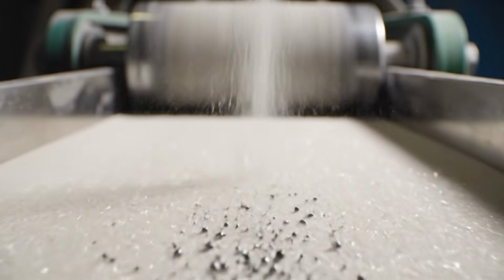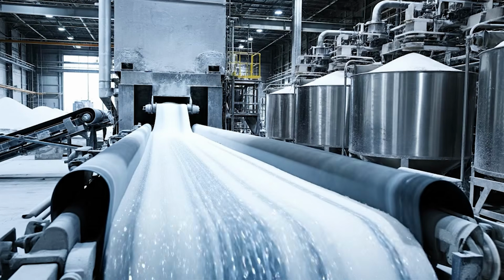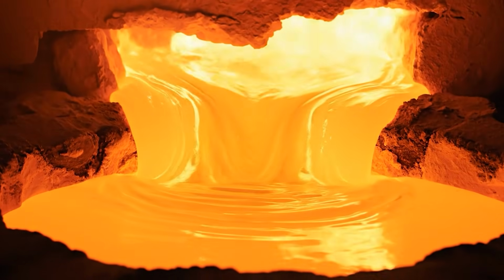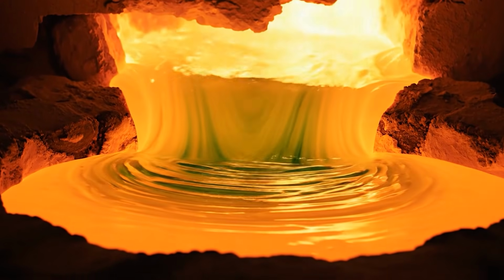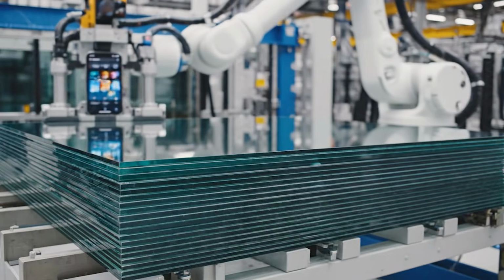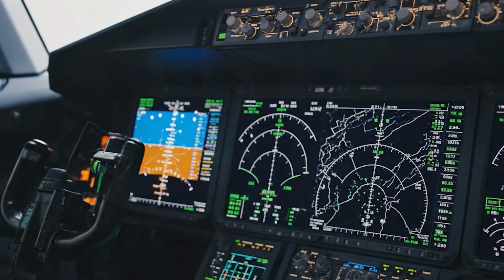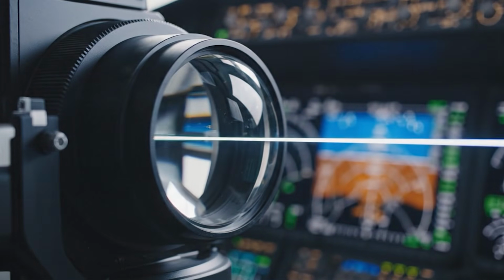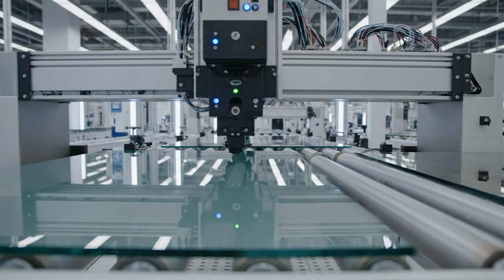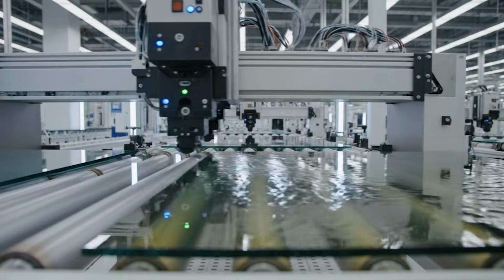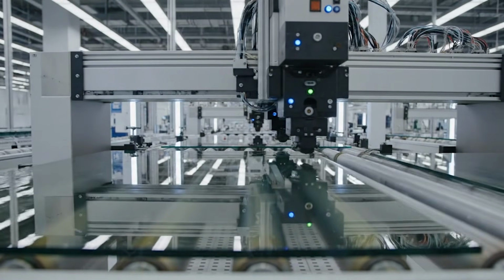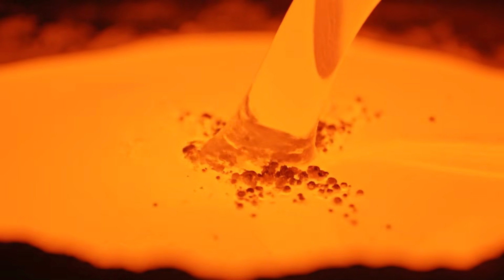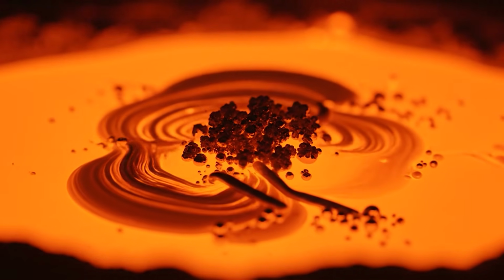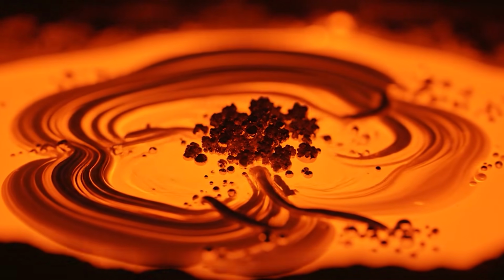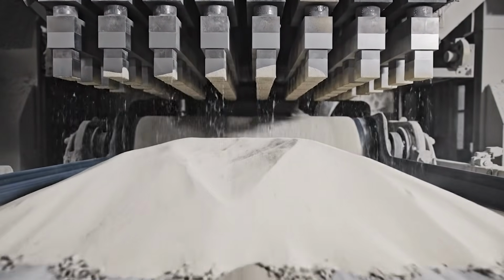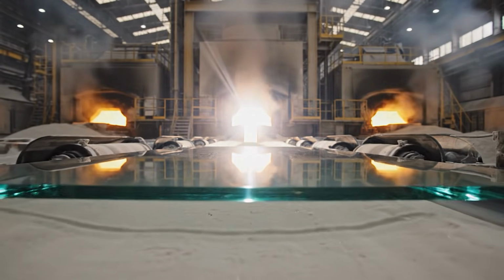The sand goes through multiple magnetic stages, each one stronger than the last, each one pulling out finer and finer concentrations of iron contamination. Here is why that matters. Iron, even in very small concentrations in molten glass, produces color. It gives finished glass a greenish tint. That tint might be acceptable in a wine bottle or a window frame, but in an ultra-strong specialty glass destined for a smartphone screen, an aircraft display, or a high-precision optical system, it is completely unacceptable. Iron ruins optical clarity. Iron also interferes with the uniformity of the melt, creating weak zones at the microscopic level that can eventually become catastrophic failures.